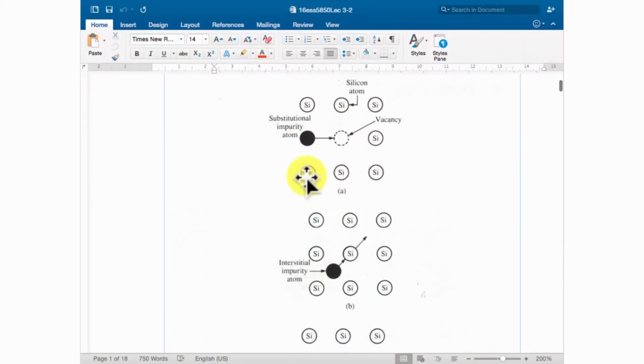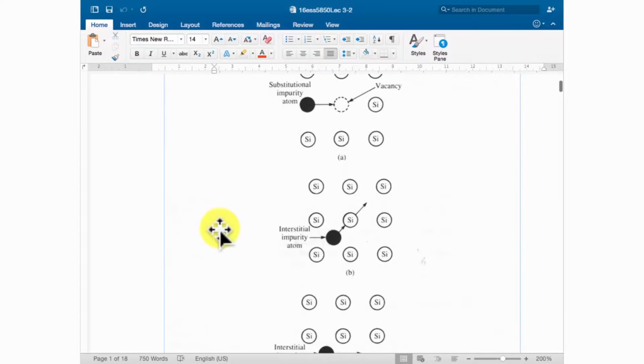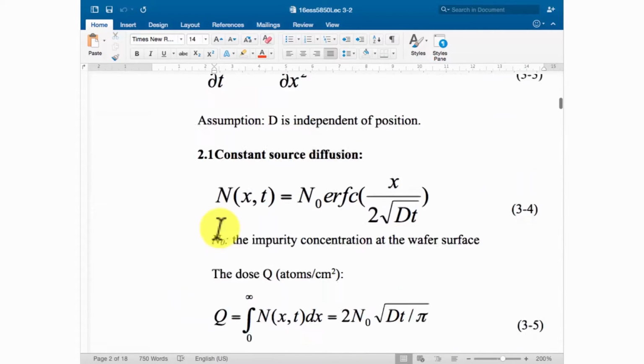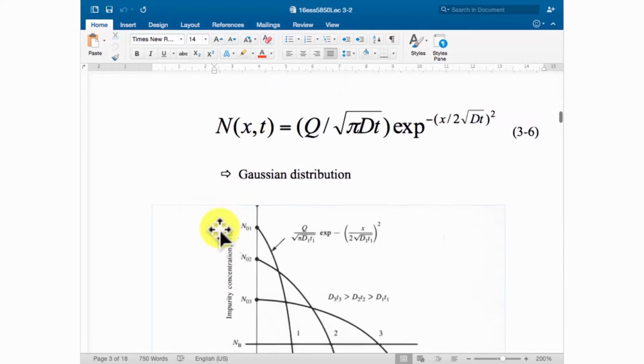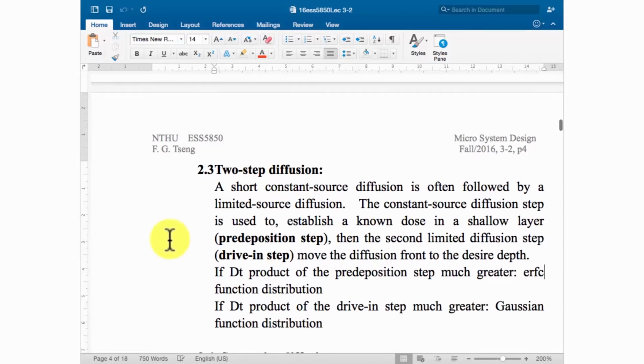That's the first thing. The second thing is that, remember, for the diffusion process, to make the impurity really work for you, you need to consider these two mechanisms. The impurity needs to replace the position of silicon. Otherwise, it cannot work properly. So the drive-in also gives the ability and the energy to allow the impurity to replace the silicon, to perform its original designed impurity functionality. So that's why we usually use a two-step diffusion process.